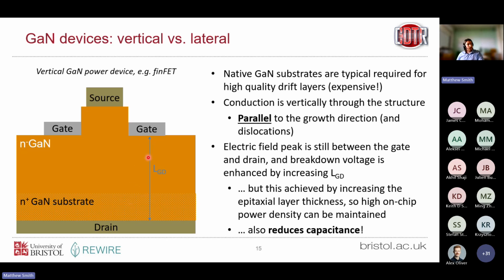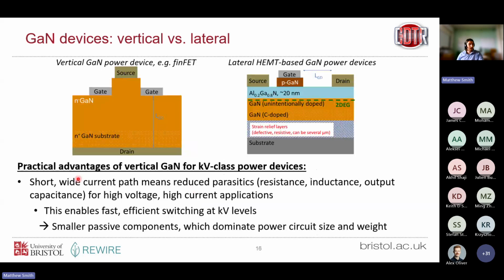But now we increase the breakdown voltage by increasing the thickness of our device. So rather than having to increase the area on the chip, we can just increase the thickness of the epi layer. So more devices per unit area, which has positive cost implications. And the capacitance also decreases as we increase our gate-drain distance. So we have this favorable scaling between breakdown voltage and capacitance in these devices.